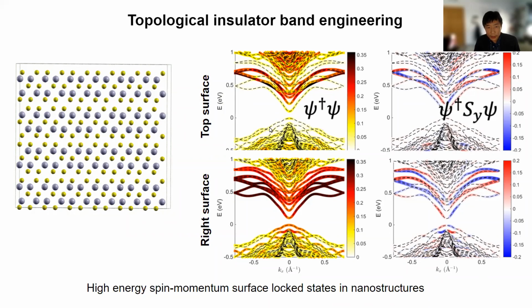What you see on the right is a plot of the band structure shown along the dashed line. The band structure is all the same, but what is different for the top surface and the right surface, as shown in this color plot, are the electron density, the surface local density of states, and also the spin polarization on these two surfaces. You can see that on these different surfaces, the local density of states and the spin polarization don't look exactly the same, because of the different termination of the bonds on these two surfaces. And we also observe that a small gap opens.